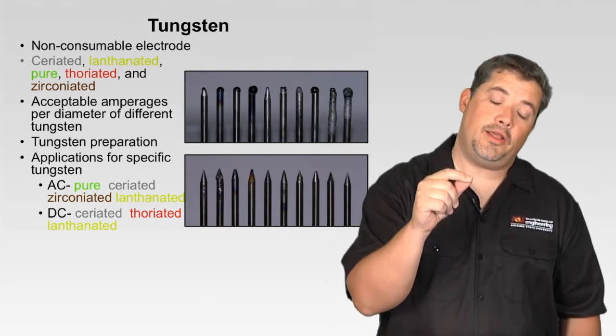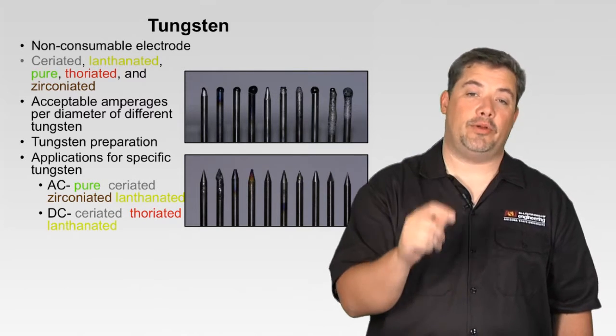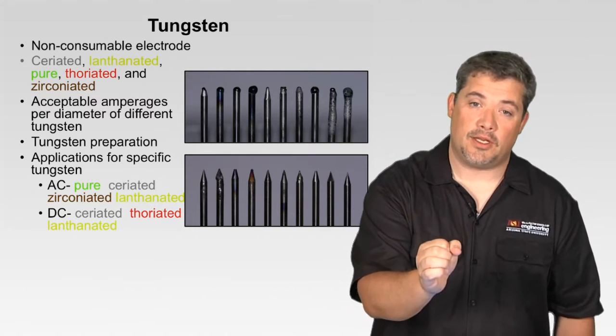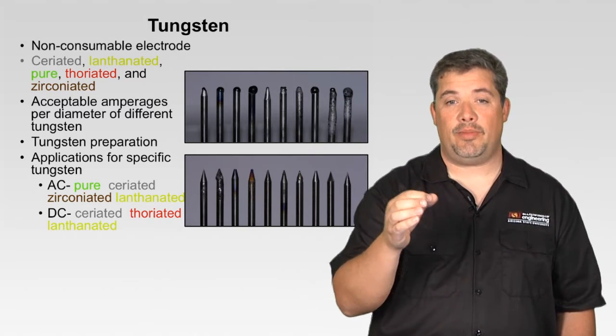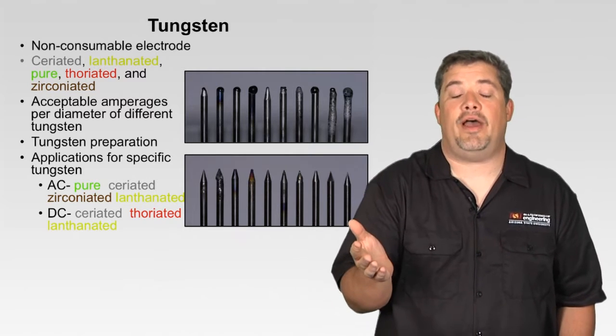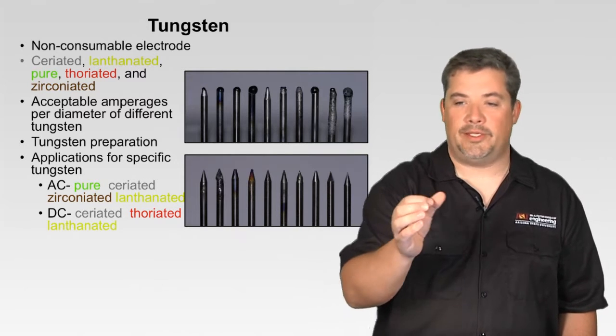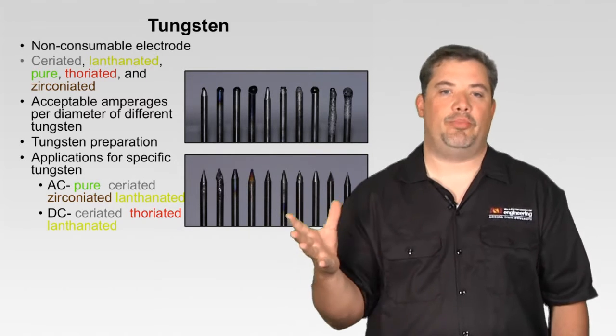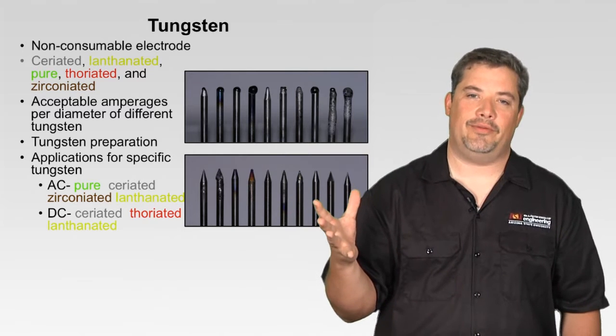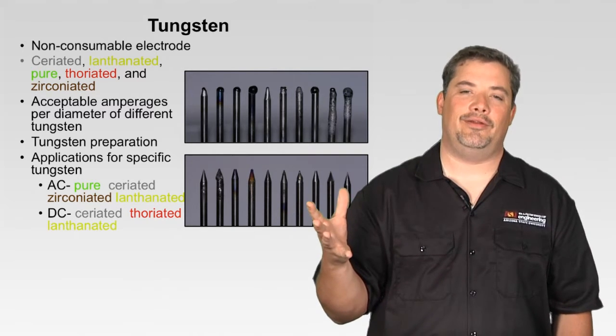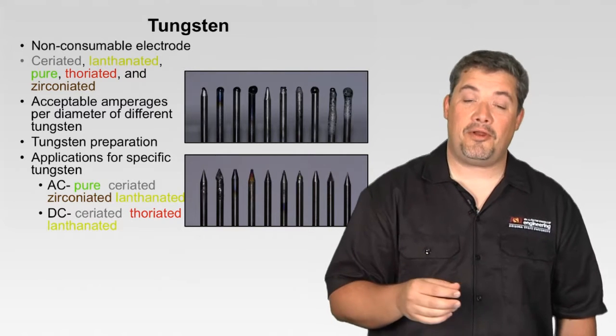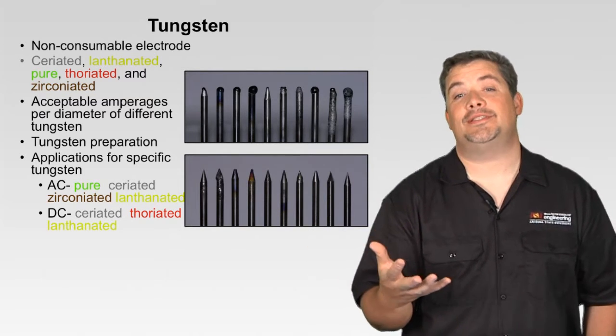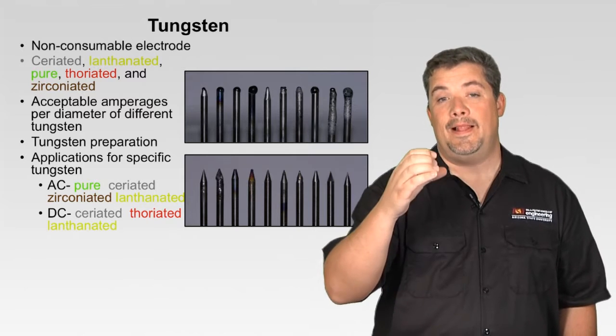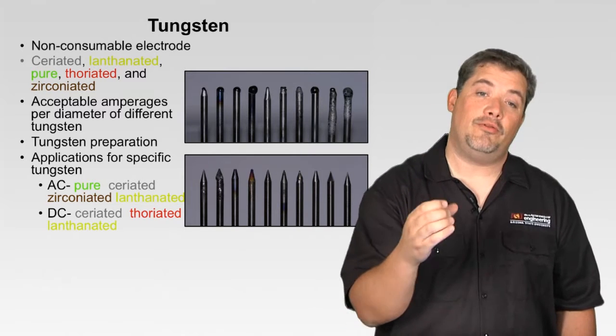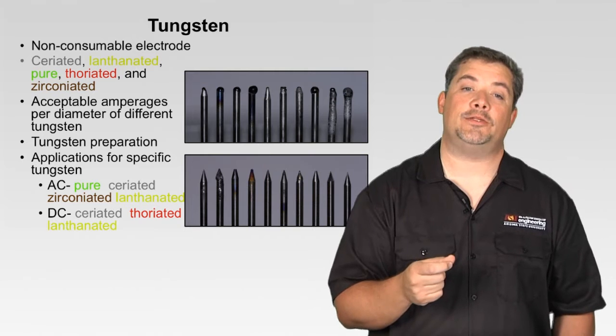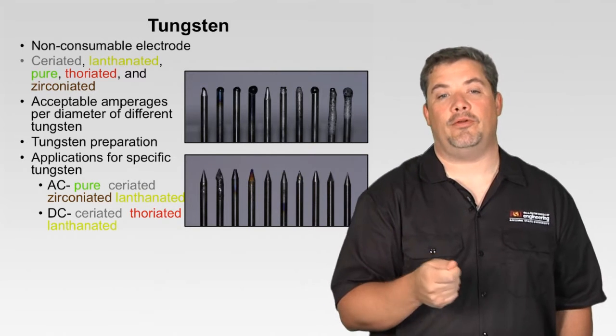If I'm welding on really thin, low amperage stuff, I want a really small diameter tungsten. Because if I have a large diameter tungsten, the best analogy I can use is, let's say I've got to fill a 5-gallon bucket of water. Do I want a simple 5/8 garden hose or a 6-inch pipe? Well, if I'm trying to fill that 5-gallon bucket with a 6-inch pipe, it's not going to work very well. But if I'm doing it with a garden hose, it's going to work well. Electricity works the same way. So the diameter of tungsten matters for how much current you're going to be putting through it. There are acceptable amperages per diameter for tungstens.